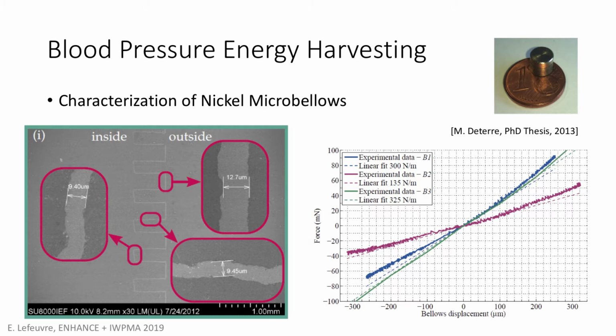On the left side, you have a cut view of the microbellows. You can see the contrast is a little bit low, I'm sorry, but you can see the shape of the cut view of the microbellows, and some measurements at different places showing that the thickness of the microbellows is between 8 and 12 micrometers, which is not perfectly homogeneous, but the hermeticity was totally achieved, which was an important point.